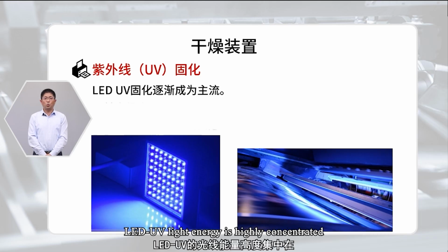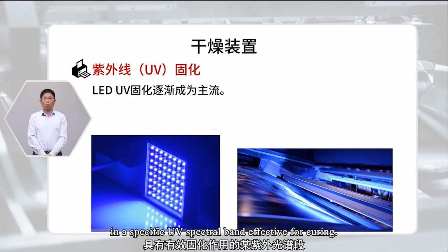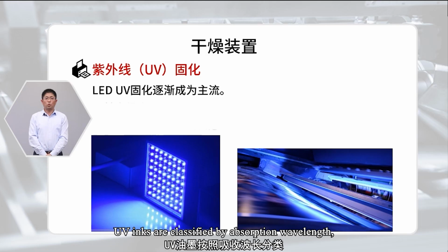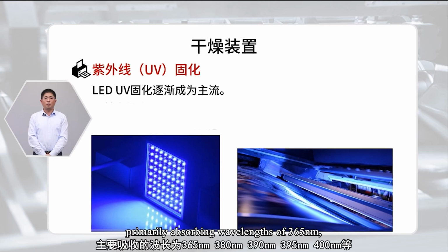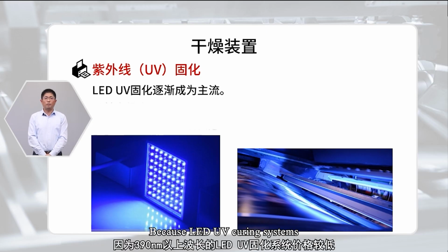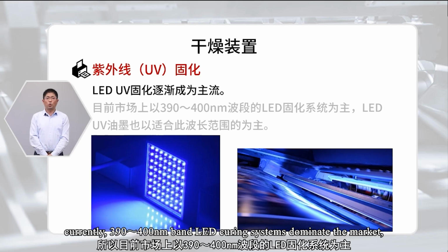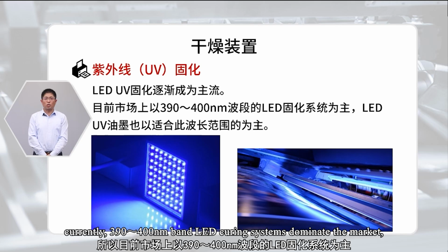LED UV light energy is highly concentrated in a specific UV spectral band effective for curing. UV inks are classified by absorption wavelength, primarily absorbing wavelengths of 365 nanometers, 380 nanometers, 390 nanometers, 395 nanometers, 400 nanometers, etc. Because LED UV curing systems with wavelengths above 390 nanometers are less expensive, currently, 390 to 400 nanometers band LED curing systems dominate the market.